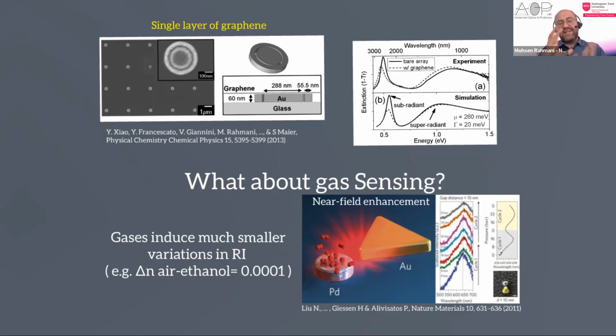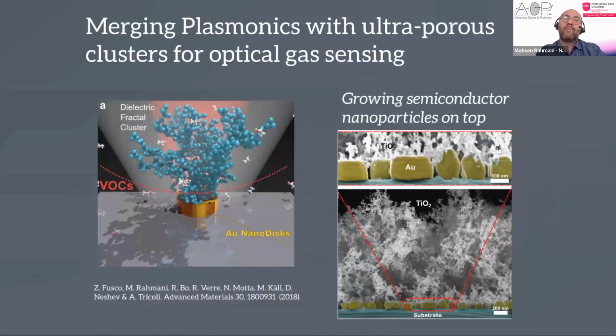So the issue of this strategy was that these palladium materials get saturated at some point when a lot of hydrogen is already embedded there. So you need to heat them up to regenerate the sensor. So plasmonic nanostructures for gas sensing have been still a big question and a big direction of research. And we also were working on that, and it is the way we proposed to use these nanostructures.